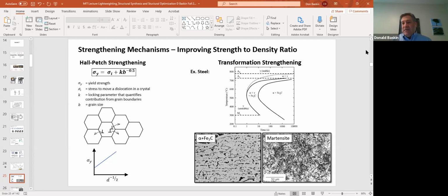That turns it to austenite. Then you can quench this austenite, and if you quench it fast enough, there's not enough time for the austenite to turn back to ferrite, or completely back to ferrite. And what you can get is what's called a martensitic material. So very little ferrite, but you have martensitic material.